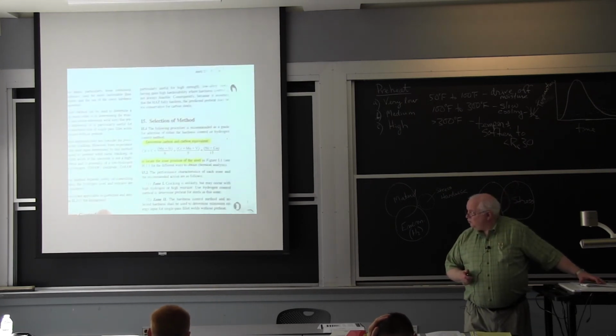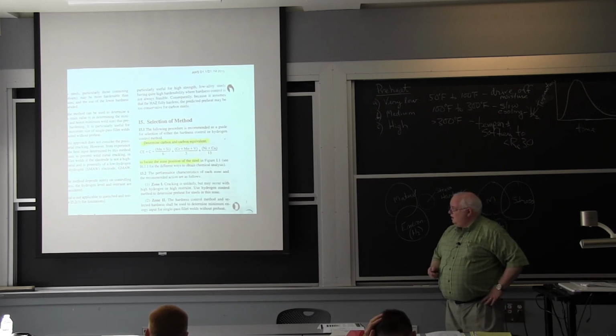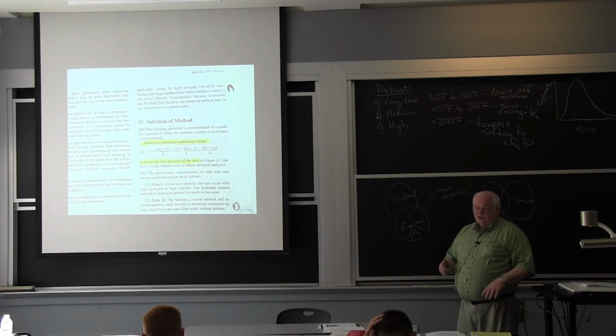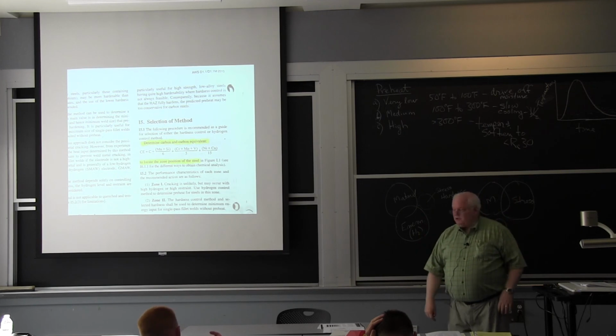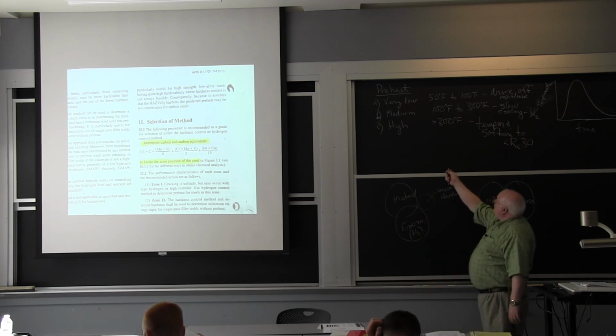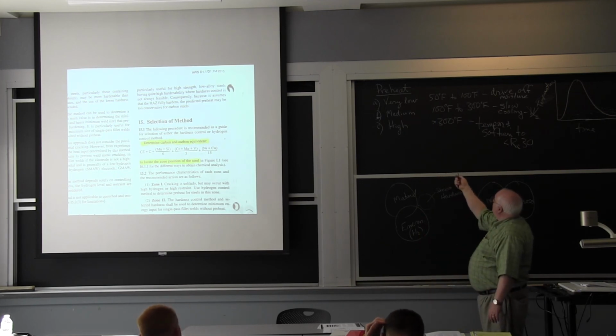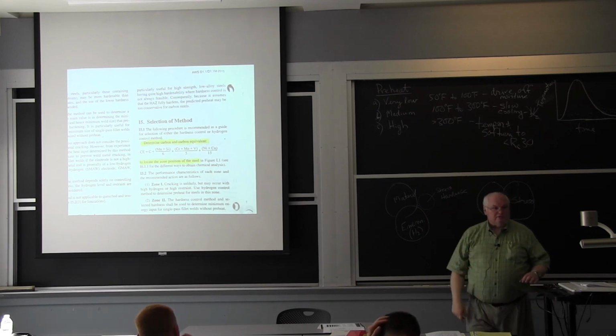Okay, so the first thing you do in hardness control is to determine whether you're in zones 1, 2, or 3. If you're lucky and you're welding bridge steels and stuff like that, or HSLA steels, you're going to find you're in zone 1, and you don't have to do much more than just come up 50 to 100 degrees to get the moisture off. Okay?